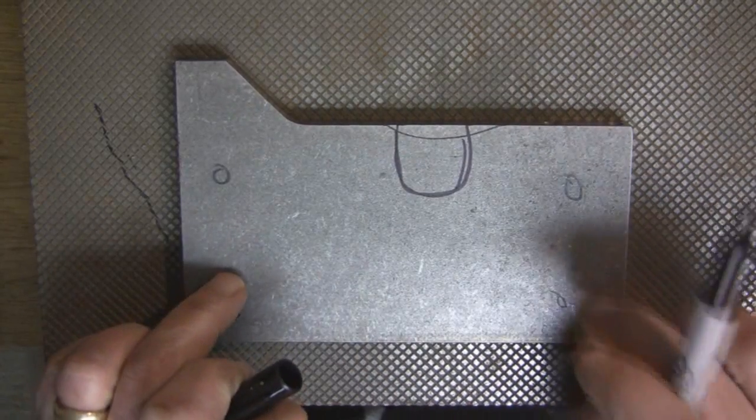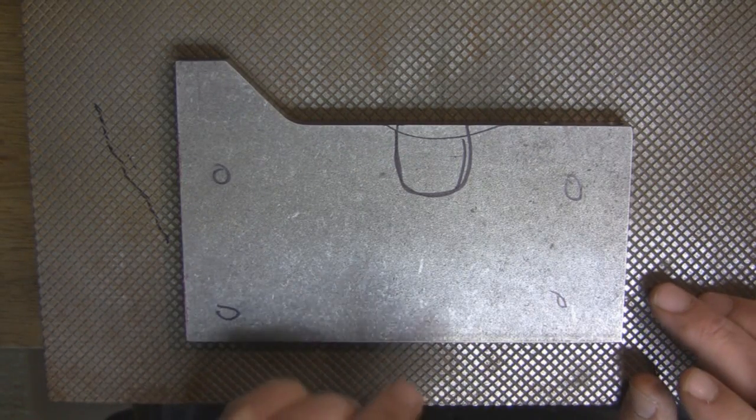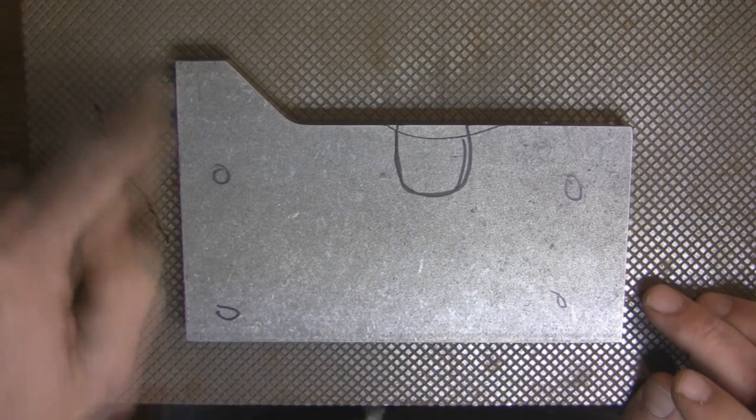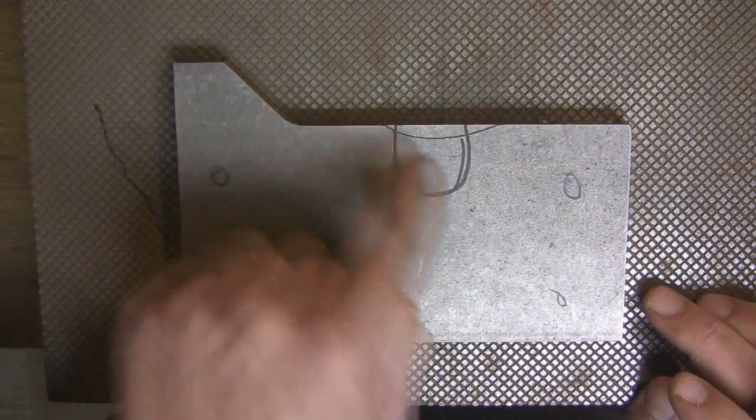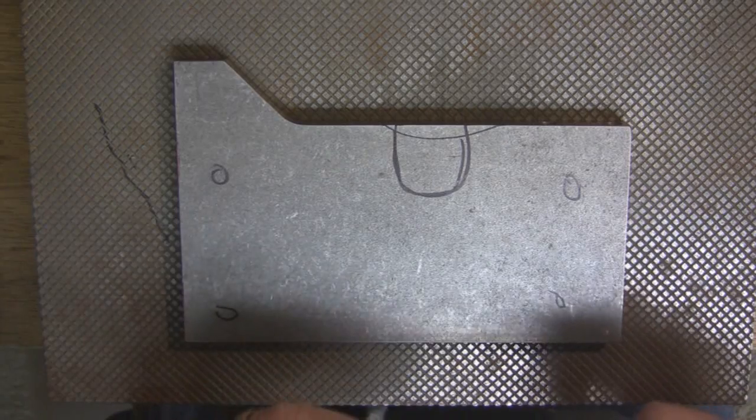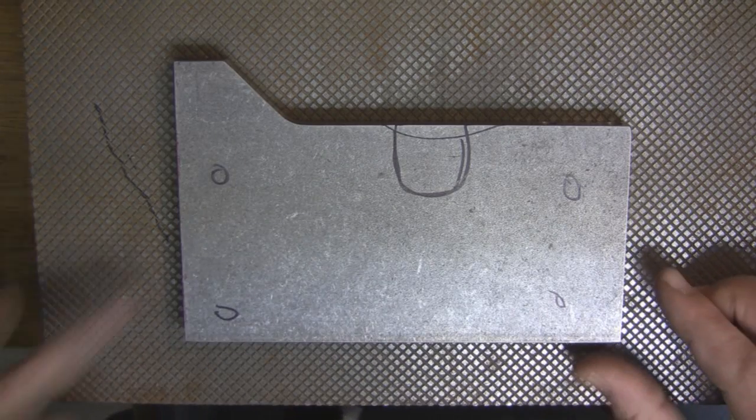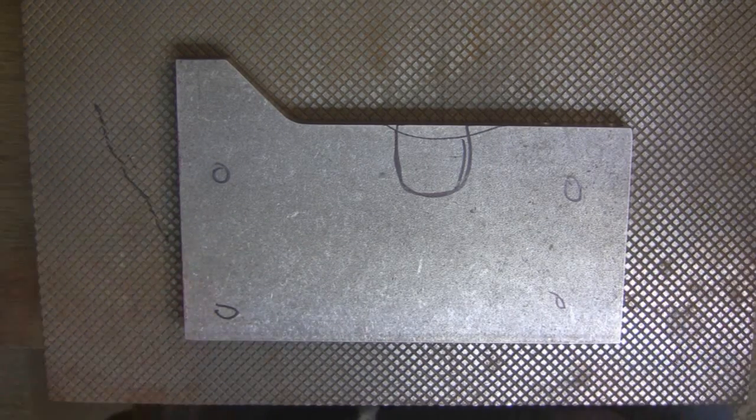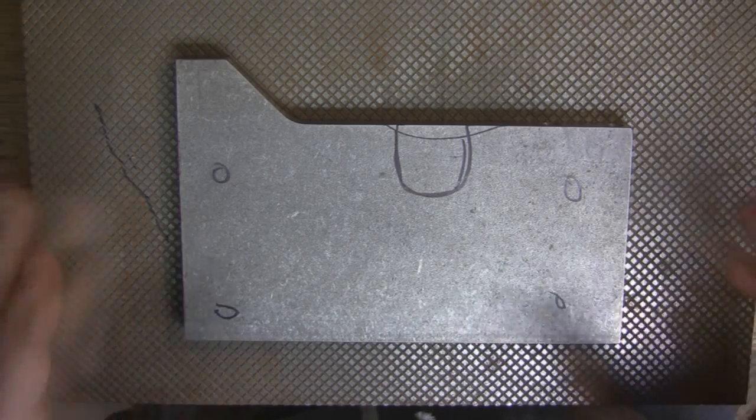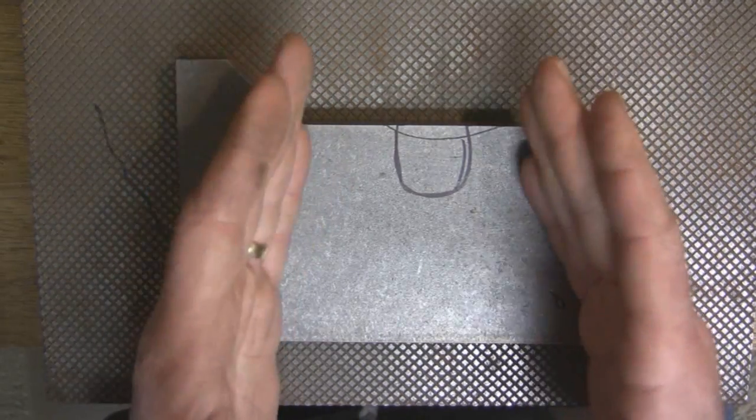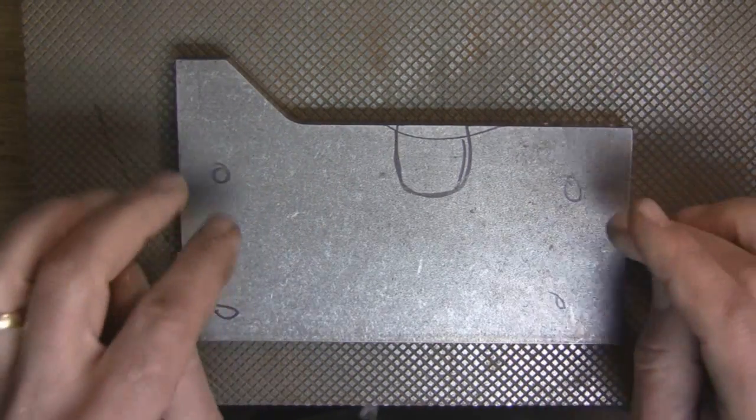So caution when using cold roll, and this is a good note to designers. If you're looking for one thousandth tolerances on shapes on the outside, forget it. And I told my manager after I finished thirty-two of these, and reground this to get it perfect, they might be different tomorrow morning. This might just never settle down.